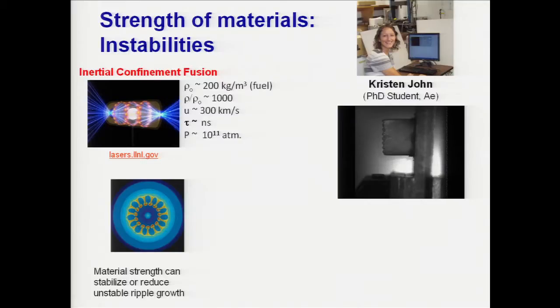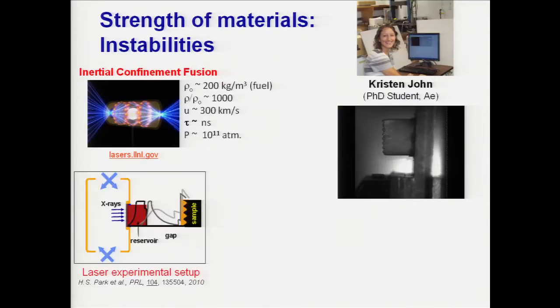One idea proposed by the scientists at Lawrence Livermore National Lab is a very clever one: put ripples on a metallic sample, which is the capsule material, and then look at the growth of the ripples subjected to the same laser loadings, but now a planar loading, and watch the growth of these ripples. And by watching the growth of the ripples, one can infer the strength of the material.